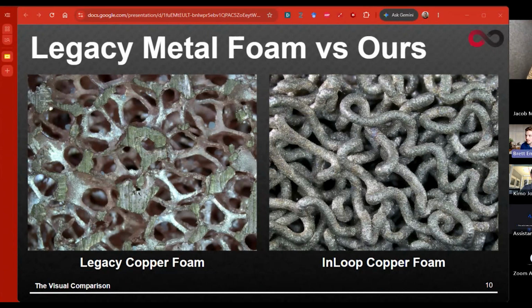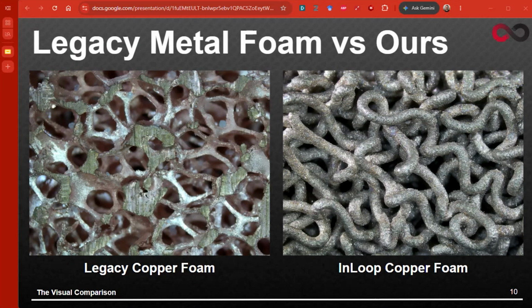To add a little bit onto that as well, the actual shrinkage characteristics are typically not as strongly related to the density of the material so much as the bulk feedstock. So as long as your powder fill in your feedstock is consistent and your post-processing routine is consistent, it is fairly predictable.